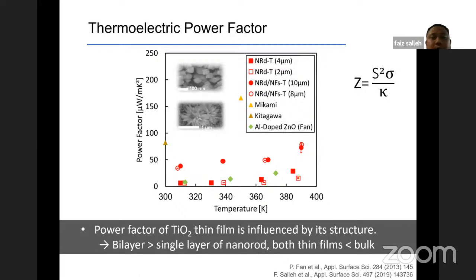And then if we look at the temperature itself, we can see here that the thermoelectric power factor of that nanostructured TiO2 depends only weakly on the temperature until around 380 Kelvin. However, above that, we can see a little bit of dependency on the temperature. Comparing with the bulk TiO2, we can see that it is very dependent on the temperature. So we can also say that we can have a stable thermoelectric power factor in this temperature range, around 380 Kelvin, something like that.